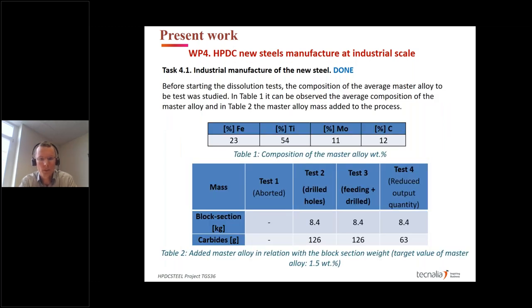So we tried several tests at the Institute of Iron and Steel Technology. The first test was aborted because of some instabilities. The second test was about the drilled holes. We got a block section of 8 kilograms, and the master alloy feeding was almost 130 grams. The third test had a feeding system implemented for one part of the ESR ingot, and the other part was with the drilled holes. We also implemented approximately 130 grams. The fourth test was again a combination of feeding and drilling. However, I have to say that test number two and test number three were more or less